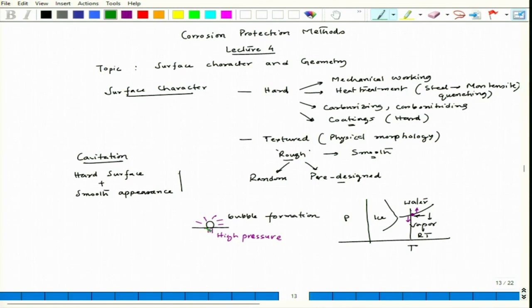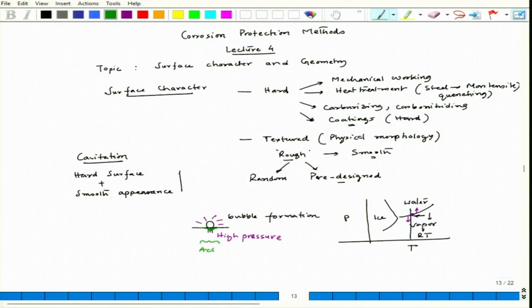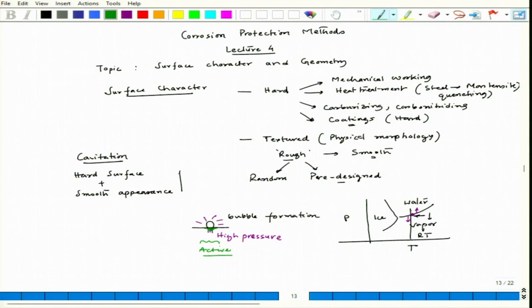If deformation occurs, there could be dent formation. Once dents form, the next operation cycle where water is sucked in through the inlet means those dented points become nucleation sites for the next round of bubbles. This dented zone becomes an active zone with higher dissolution ability due to electrochemical dissolution of metal ions. So we have two factors: bubble formation and collapse leading to stress, and that stress leads to deformation which creates an active zone, causing further corrosion.